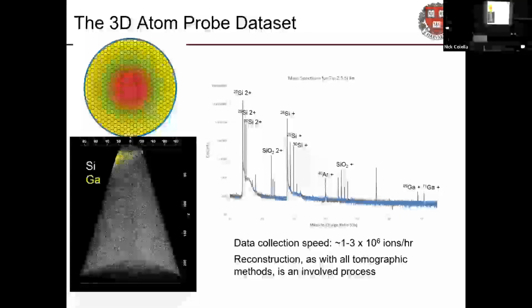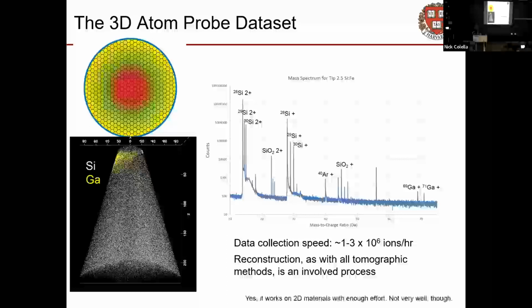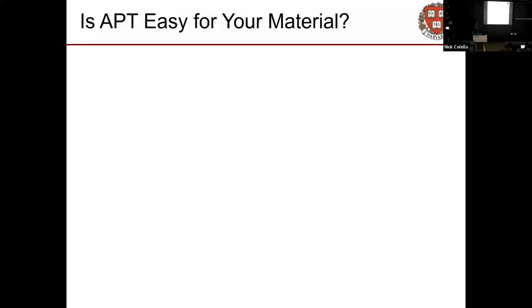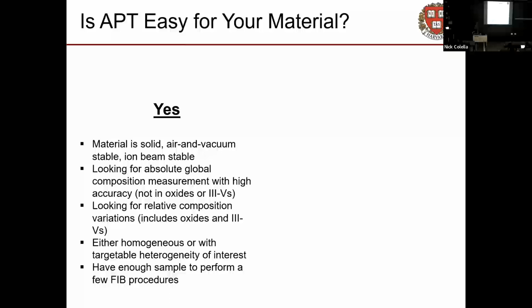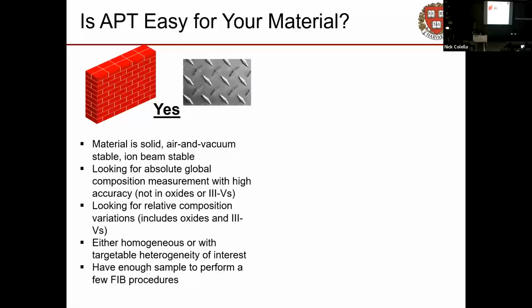Fabulous. And then we put them in 3D, and we have this nice spinning map of where they all were. Cool. It works on 2D materials, but I don't know why you would bother. You're only going to get a tiny amount. So, materials this works really well for: solids, don't bring me any gases. Things that don't mind being in UHV, which means they've got to be vacuum stable, they've got to tolerate various parts of the setup. Materials for which you're looking for absolute composition measurements, everything but oxides and III-Vs. We're not going to get absolute measurements on those for reasons. But if you want relative composition measurements, meaning you think there's a difference between point A and point B, yes, those we can do even in oxides and III-Vs.